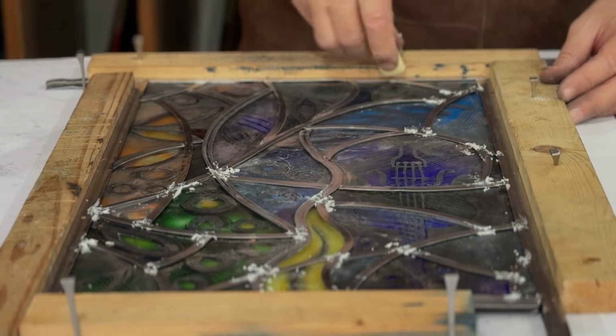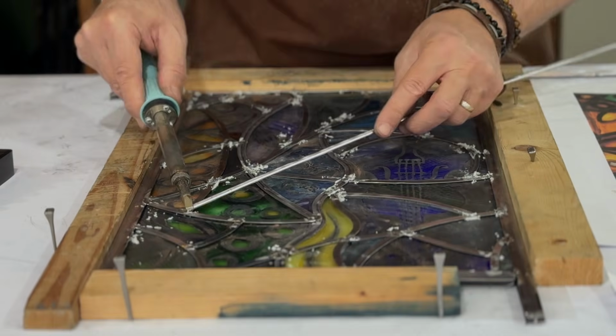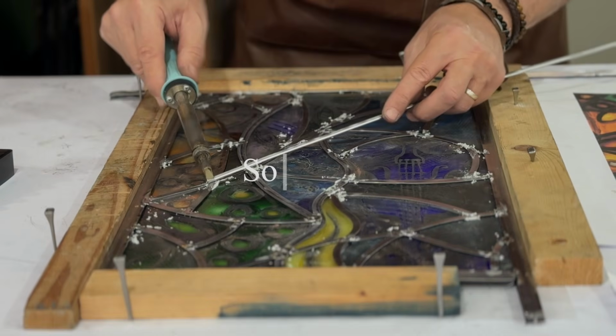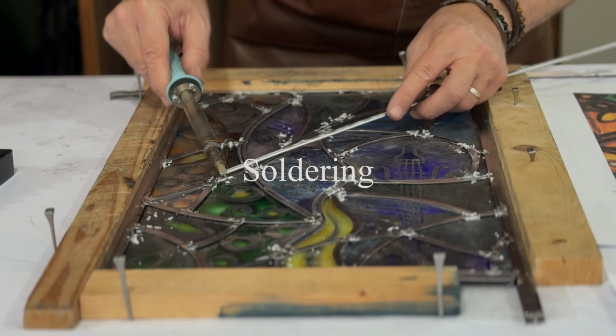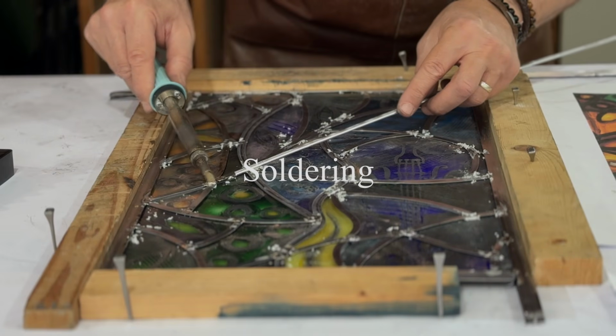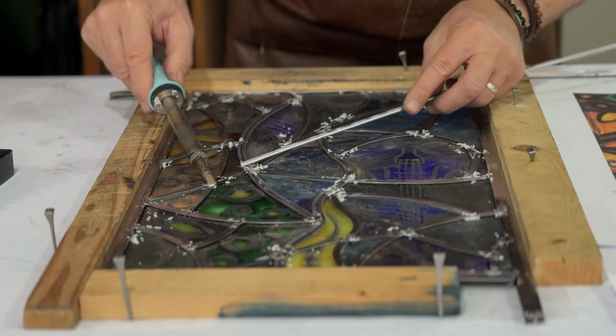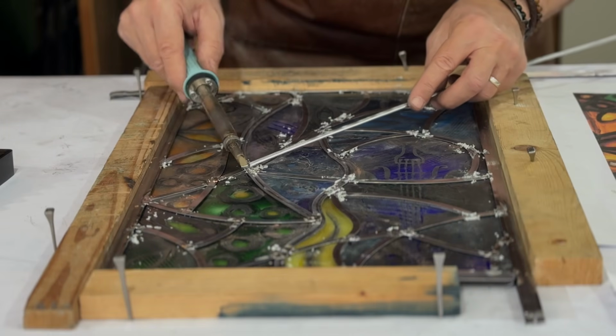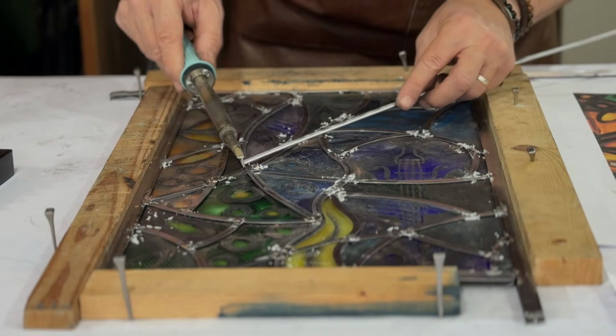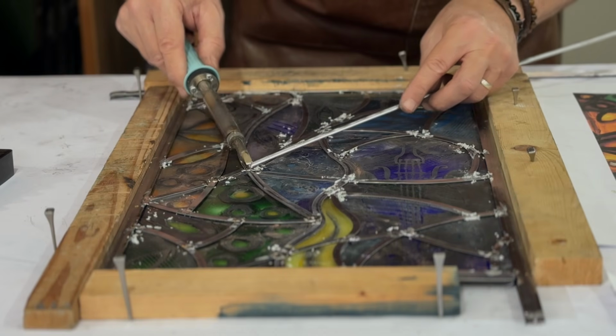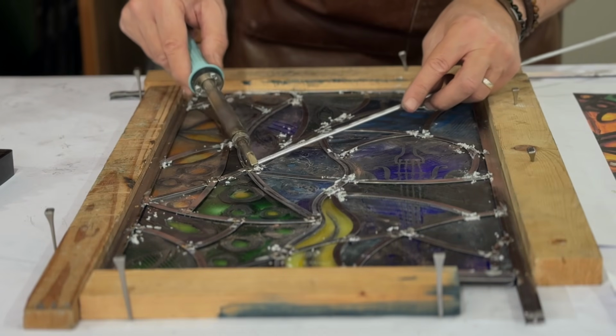Today I'm using a tallow candle, which is an animal fat, usually sheep fat, but you can use water-soluble fluxes or acid-based fluxes as well. I'm using a Weller 100-watt electric soldering iron with some blowpipe solder, 60% tin, 40% lead.